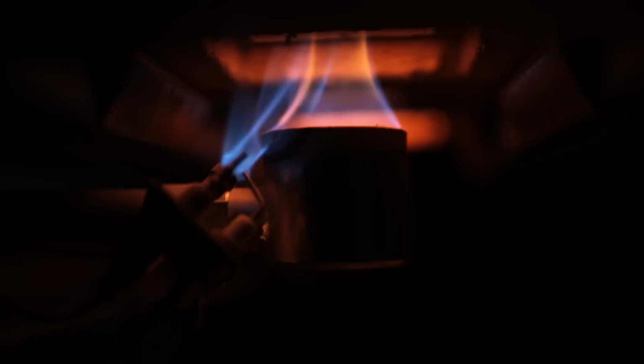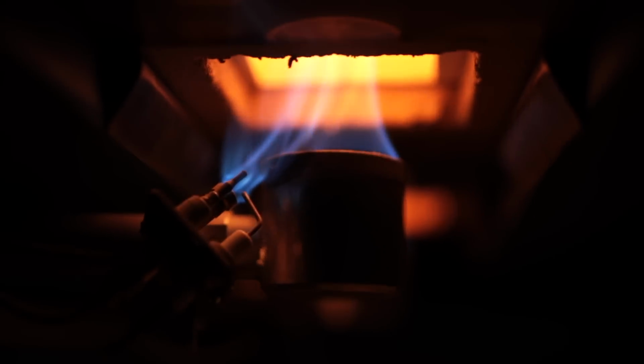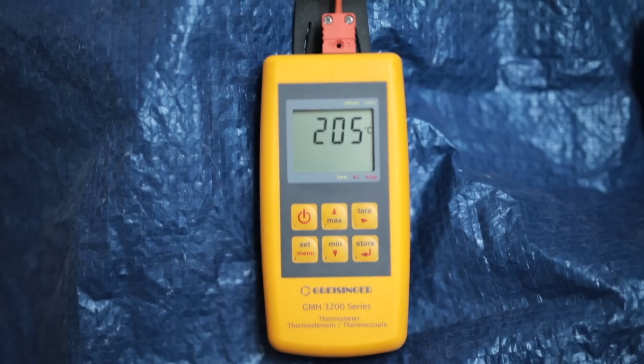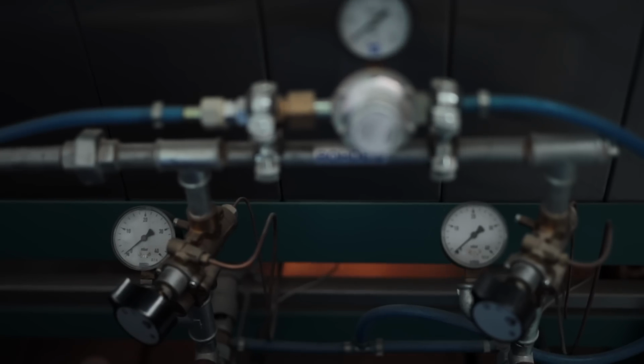With the kiln fully packed, it can be lit the following morning. I usually start at about 7 AM on the dot, and the entire process takes about 8.5 hours. During the early stages of the firing, I raise the temperature gradually, as pushing it quickly is never a good idea. Once 860 degrees Celsius is reached, I start the reduction.